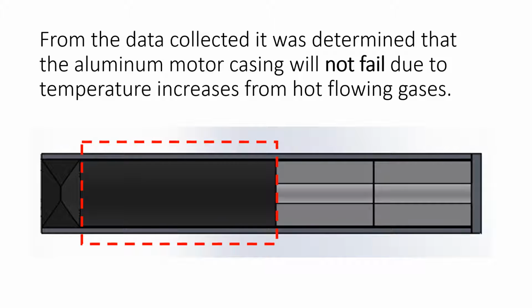From the data collected, it was determined that the aluminum motor casing will not fail due to temperature increases from hot flowing gases. The next step to ensure the viability of pseudo-staging will be to determine how long the phenolic liner can be exposed to high temperature gases before ablating. Another important step will be to determine the thickness of the solid fuel wafers that must be included to separate the stages. These wafers need to be sized such that they will not break up under pressure and clog the nozzle. They also need to be large enough to prevent upper stages from burning prematurely.